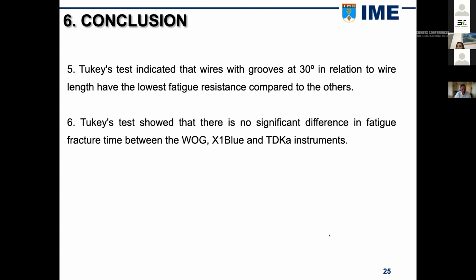Tukey's test indicated that wires with grooves at 30 degrees in relation to wire length have the lowest fatigue resistance compared to the others. Tukey's test showed that there is no significant difference in fatigue fracture time between the WaveOne Gold, X1 Blue, and TDKa instruments.